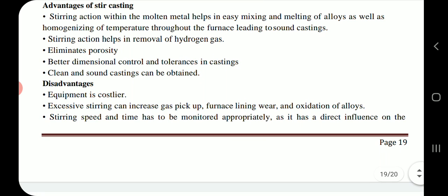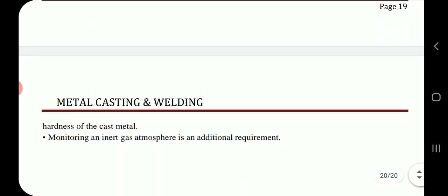Advantages of stir casting: stirring action within the molten metal helps in easy mixing and melting of alloys as well as homogenizing of temperature throughout the furnace, leading to sound castings. Stirring action helps in removal of hydrogen gas, eliminates porosity, gives better dimensional control and tolerances in casting, and clean and sound castings can be obtained. Disadvantages: equipment is costlier, and excessive stirring can increase gas pickup, furnace lining wear, and oxidation of alloys. Stirring speed and time has to be monitored appropriately as it has a direct influence on the hardness of the cast metal.